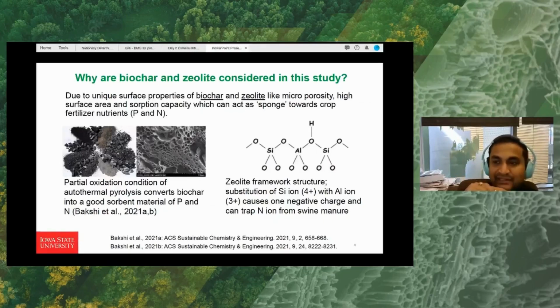For the biochar, the partial oxidation condition of autothermal pyrolysis converts biochar into a good sorbent material of phosphorus and nitrogen. We have 2 published manuscripts mentioned below if anyone is interested in reading them. We showed in this manuscript that it has a very good phosphorus absorption capacity, and in another manuscript we have shown that it can act as a slow release nitrogen fertilizer.